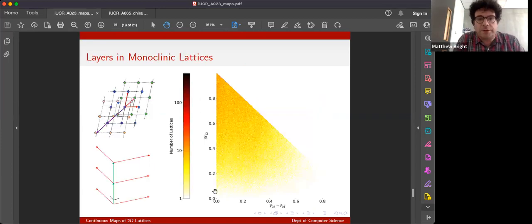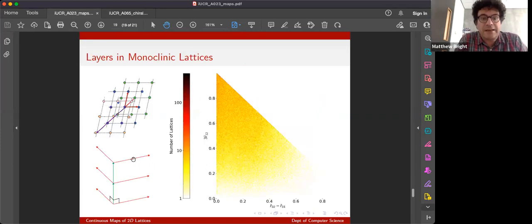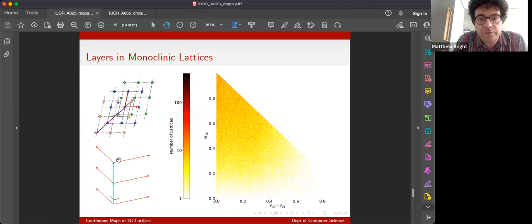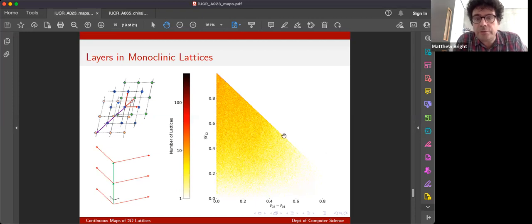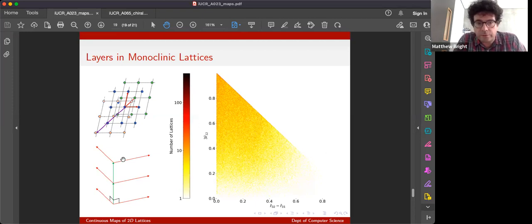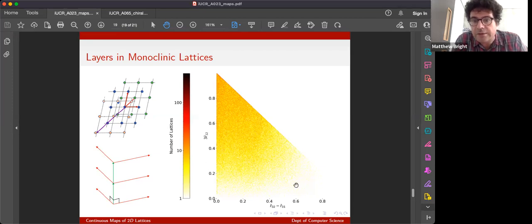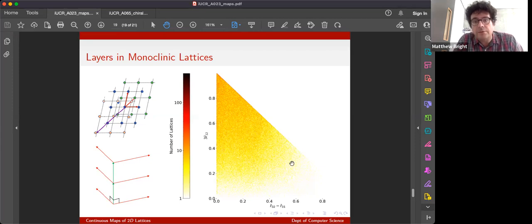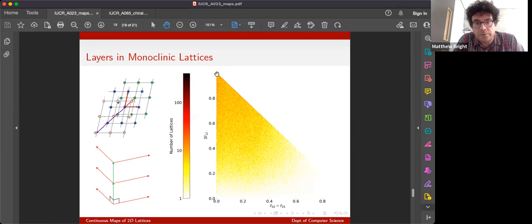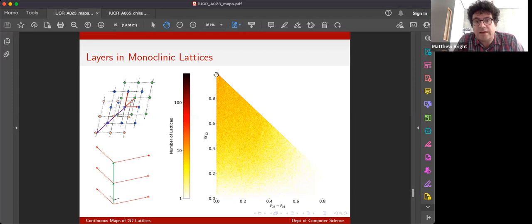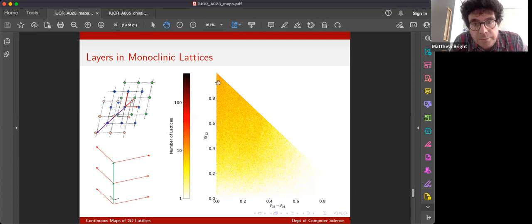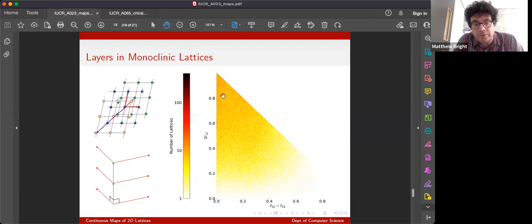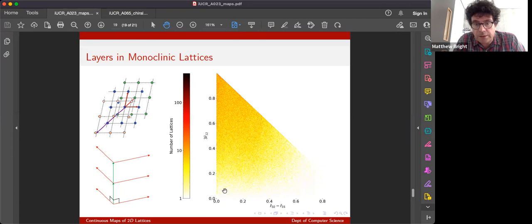If that seems a bit artificial, we can take monoclinic lattices, which are just layers of two-dimensional lattices with an orthogonal vector to each layer, separating them. And again, you see the same thing, you see that those layered lattices, the two-dimensional layered lattices are filling the space quite clearly or filling the physically meaningful bits of the space and becoming more dense towards, but becoming more dense towards the point at the top, this vertex here, which represents hexagonal lattices. So lattices sort of want to be highly symmetrical to adopt the most symmetrical configuration, but they can adopt a wide range of them.